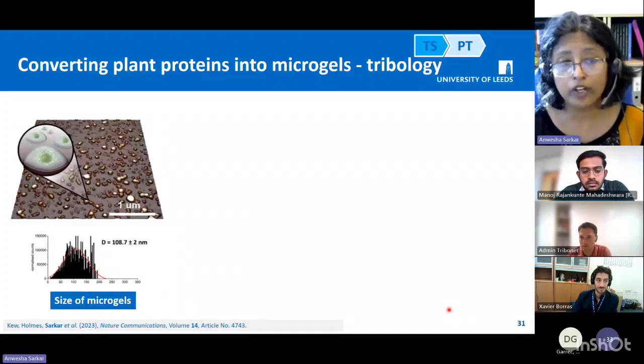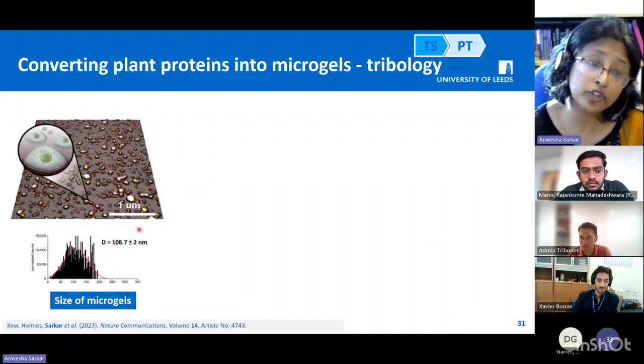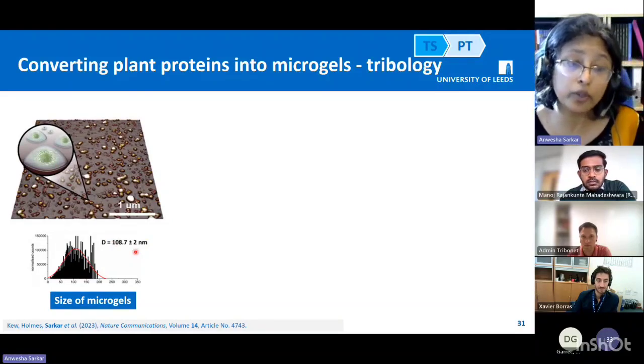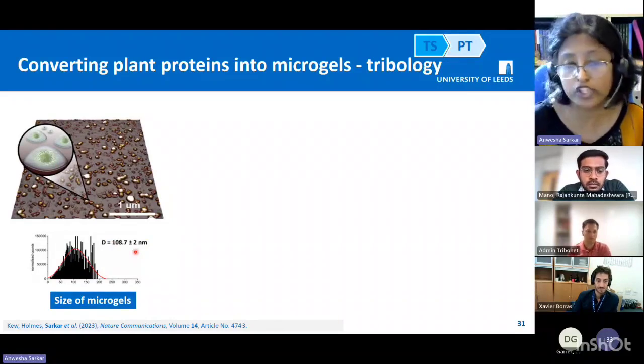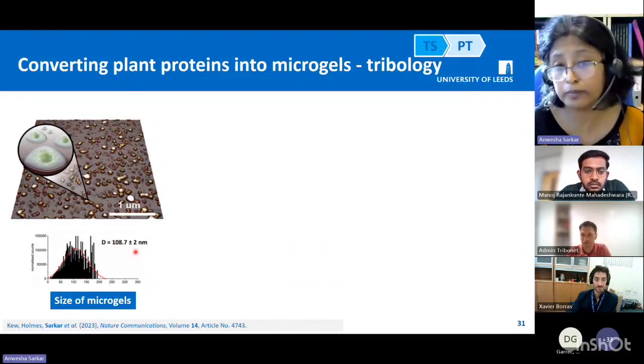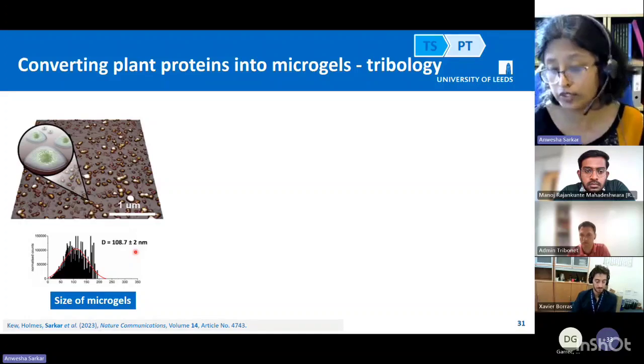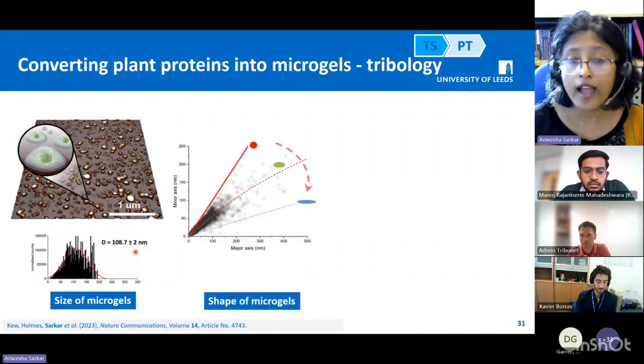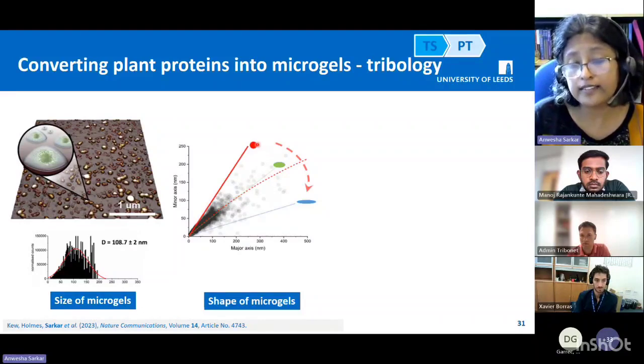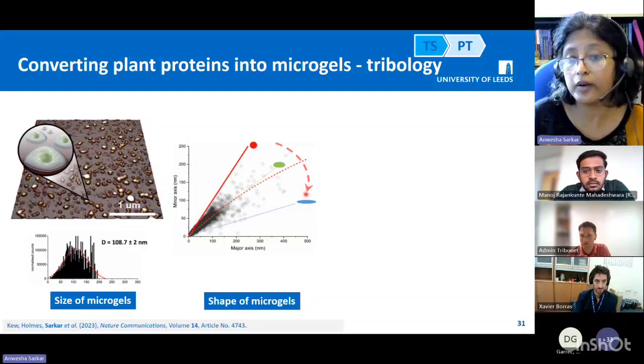Now we did the tribology, so this is the AFM. We made very small particles, but you can make them whichever size you want, depending on the pressure of the homogenizer you're using. And you can also make them different sizes and shapes. We were interested in making them spherical, but some of them were a bit more oval or elliptical shaped.